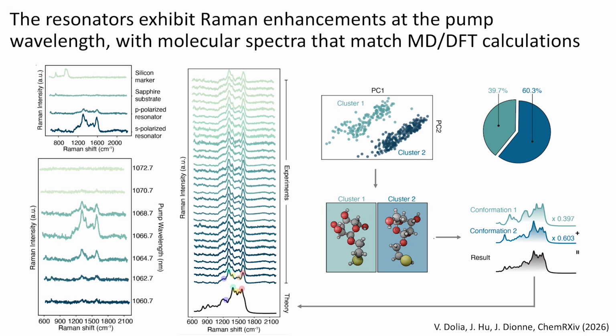And then what I think is especially exciting, and one of the more recent advances in my lab, is that we can actually do molecular dynamics and first principles calculations like density functional theory to predict the Raman spectra. So we can compute the Raman spectra. And you can see here the theory at the bottom agrees quite well with the experiment. What we do is molecular dynamics to figure out the conformation of the molecule or the macromolecule. And then we take those different conformations, we feed them into density functional theory, which, by the way, is computationally expensive, but with advances in quantum compute, it's actually becoming much faster.